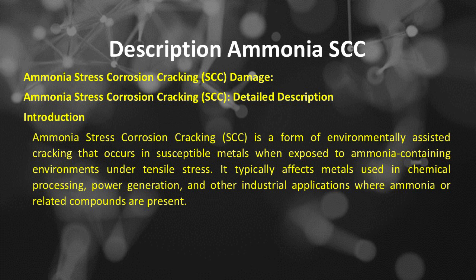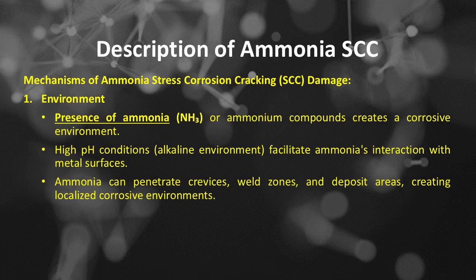present. Mechanisms of ammonia stress corrosion cracking damage include, number 1, environment. Presence of ammonia, or NH3, or ammonium compounds creates a corrosive environment. High pH conditions, an alkaline environment, facilitate ammonia's interaction with metal surfaces. Ammonia can penetrate crevices, weld zones, and deposit areas, creating localized corrosive environments.